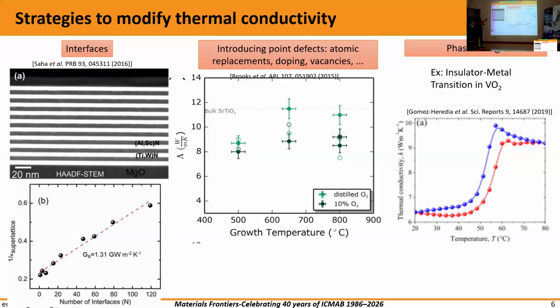This is a superlattice. The other way is introducing defects like vacancies. If you increase the density of defects, we're going to have more phonons scattered, and the thermal conductivity is going to decrease when you're increasing the number of defects.